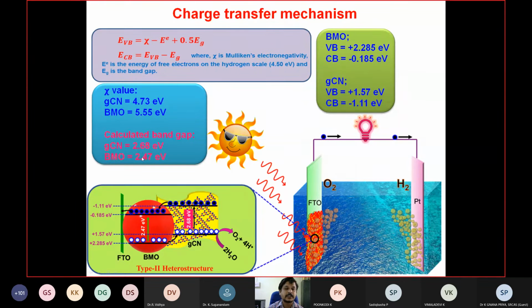from the diffuse reflectance spectra that I showed for that material. We substituted these values in this formula and calculated the valence band position and the conduction band position for graphitic carbon nitride as well as bismuth molybdate. Then based on that, we have drawn the structure. Accordingly, based on this energy level, the graphitic carbon nitride will undergo charge separation, and it oxidizes the water and produces oxygen as well as hydrogen.